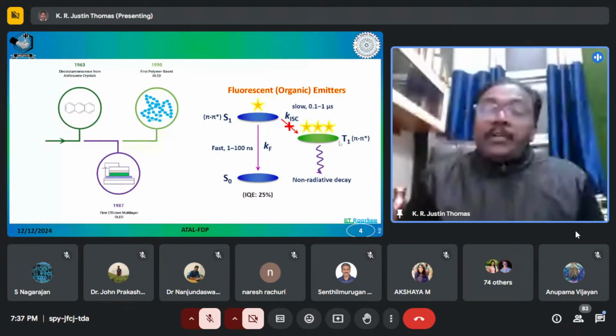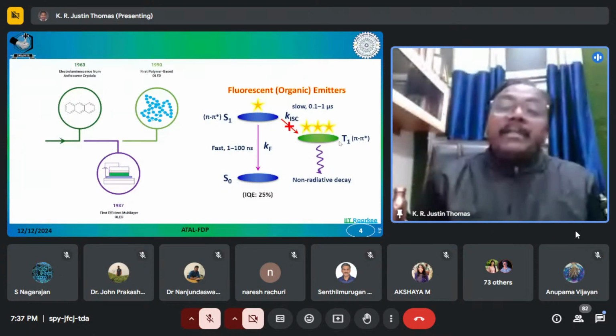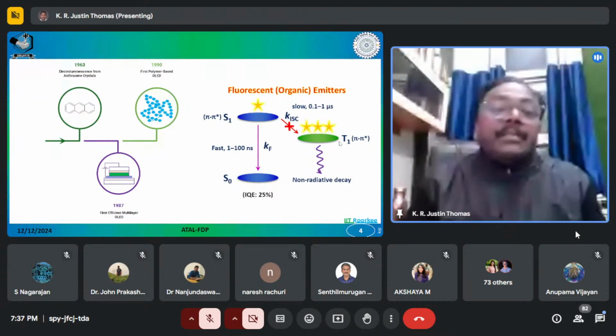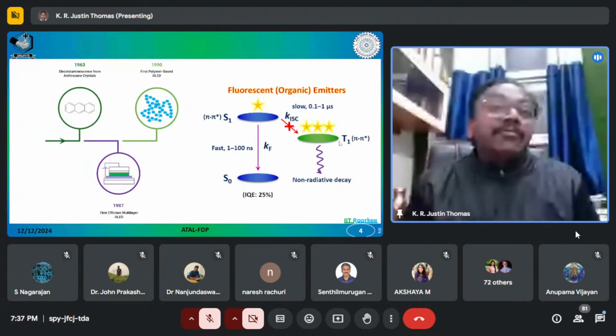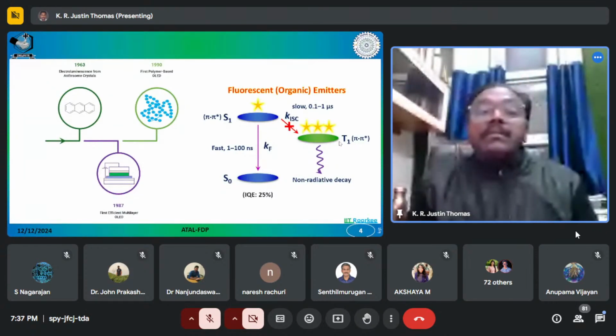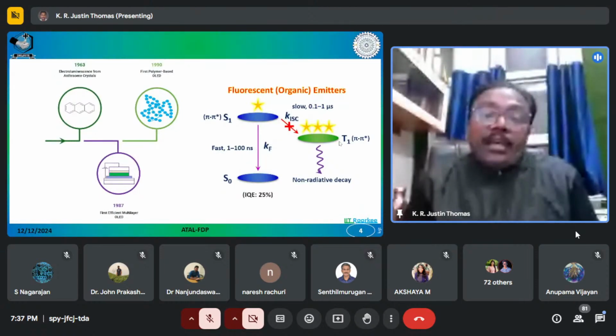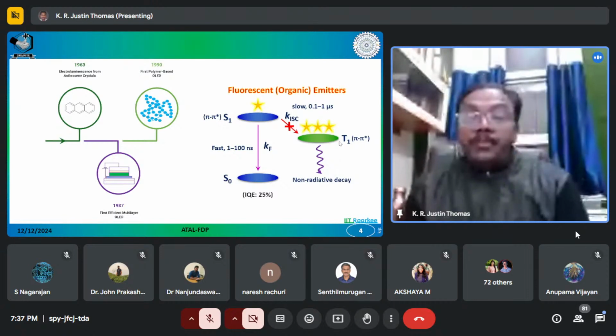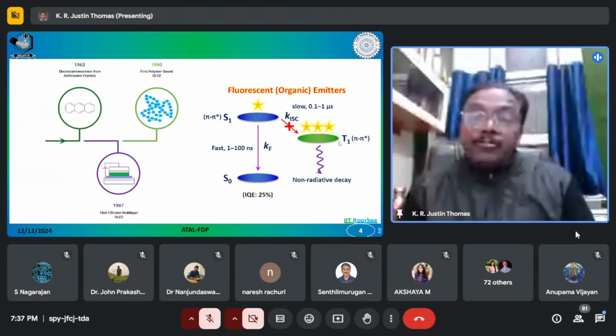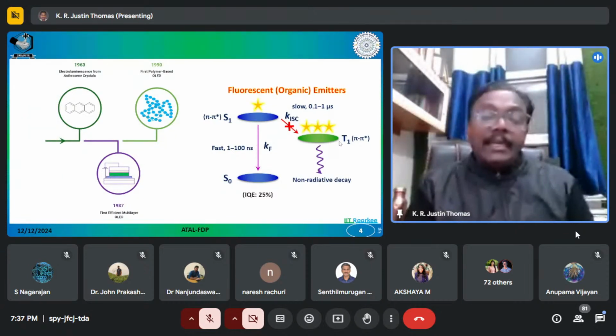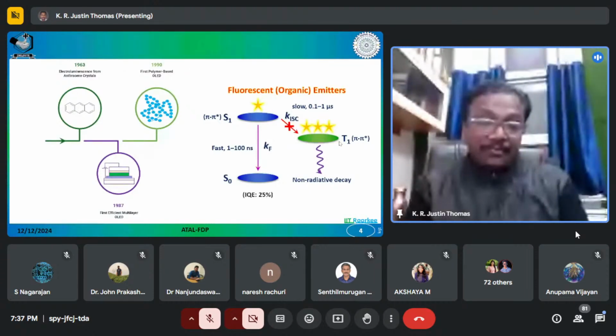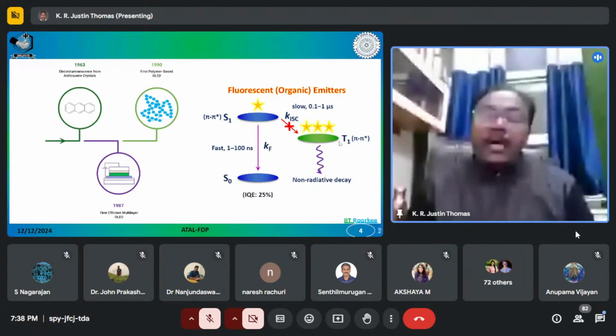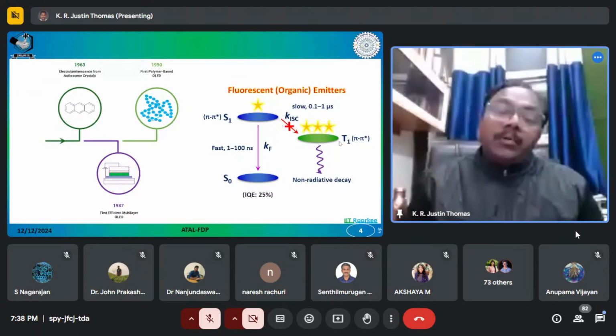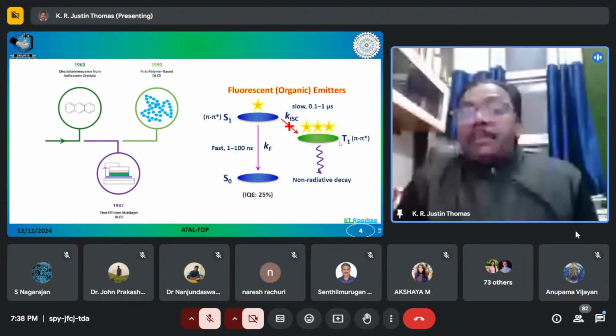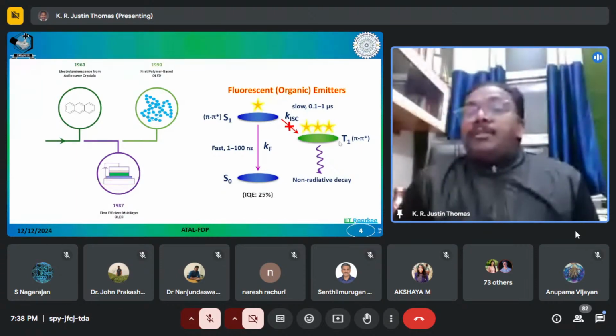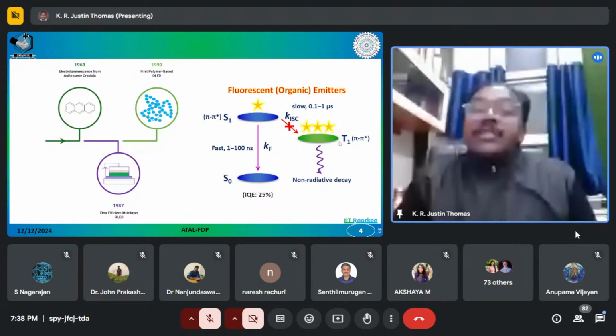So if you look at an LED, what happens is when the excitons are formed, 25% of the excitons have a singlet configuration, while 75% of the excitons have a triplet configuration. That is because the holes and electrons combine together to produce the excitons, and they can combine in 4 different forms. In one form, the spins up and down make a singlet state, while in the others, where they are both up or both down, they are aligned. So in those cases, it's a triplet state. Okay, so you will have 3 triplet states. So that is altogether coming to 75%.